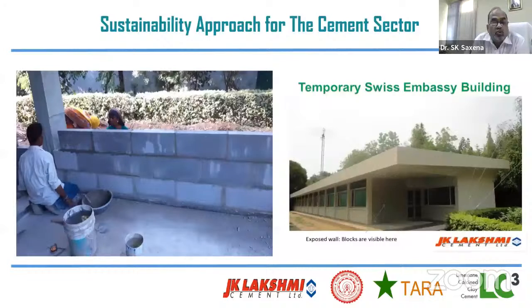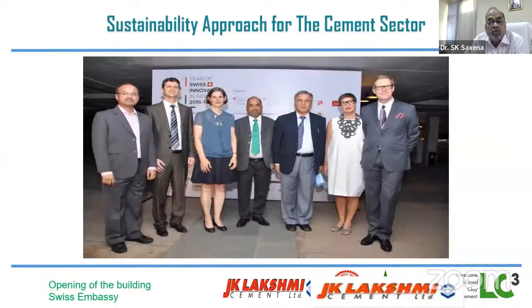where this has to be used, and we produce this AAC blocks with the 100% replacement of OPC by LC3 in the same proportion, and we supplied around 145 meter cube. And this building has been built with the exclusive use of this AAC block, exclusively manufactured with the use of LC3, replacing ordinary Portland cement. Now, this is a green building which has been manufactured, and this is a photo which has been taken at the time of inauguration of that administrative building in Swiss Embassy.